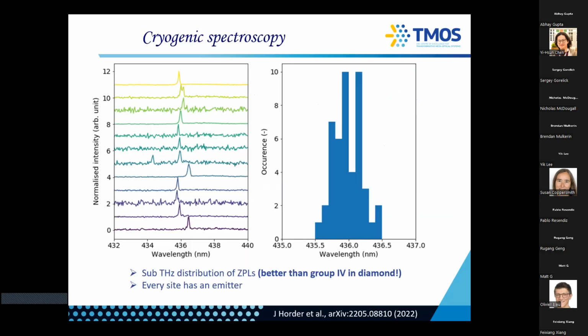Now, you can already see from this type of data that these defects are going to be good at cryogenic temperatures. So this is just a histogram of many of them. We only plotted about 10 here. There are a bit more here, and you can see that the distribution of lines falls within a nanometer. So it's like a terahertz, 2 terahertz maybe. And this is actually better than the best defects in diamond. So there's now a lot of hype about silicon vacancies in diamond and germanium vacancies in diamond, all the group 4 that are very symmetrical, that have no permanent dipole. This is better. So the distribution of lines is very narrow, all emit around 436 nanometers.